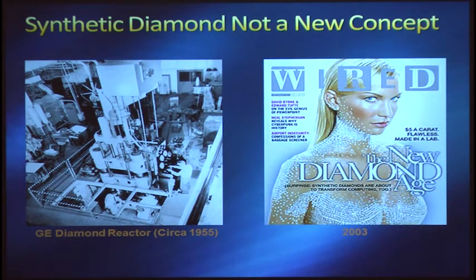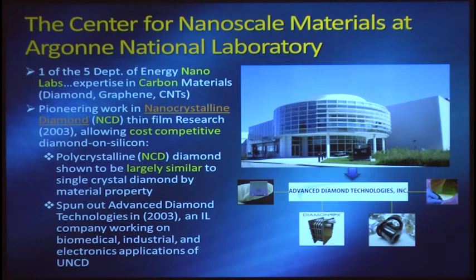We cycle forward to 2003, we have this new process called chemical vapor deposition, where we could literally grow diamond. We use either a hot filament or a microwave plasma technique, where we put a substrate inside of a reactor, and we're actually able to grow diamond on top of these things. As I mentioned, Argonne has been at the center of the more recent boom.